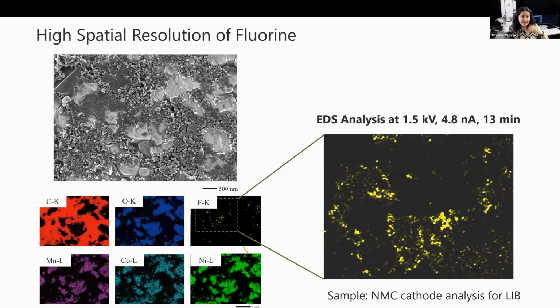One thing you will note here is that we do not see lithium in this sample. This is because when lithium is bonded to oxygen, it generates very, very few X-rays. So we will generally not be able to detect it with EDS, even with a windowless EDS detector. But we should be able to detect metallic lithium. However, we will need to use air-isolated procedures to prepare it in order to stop the lithium metal from oxidizing in air.